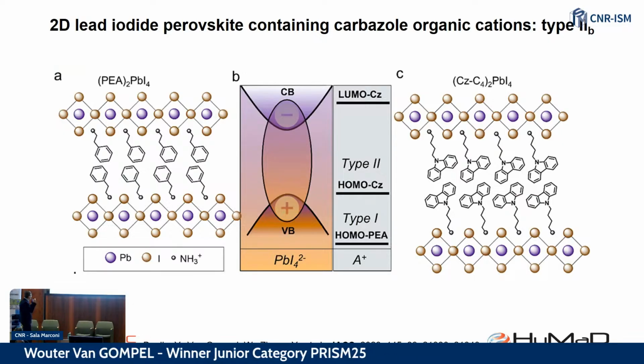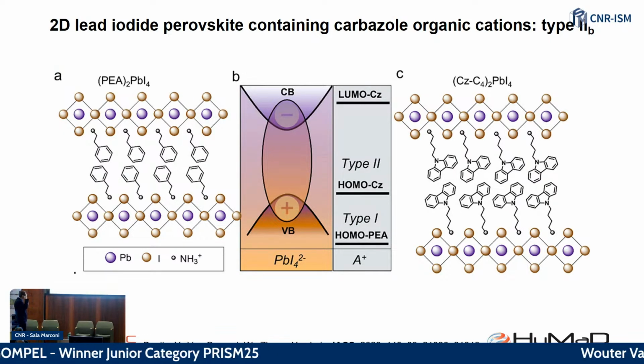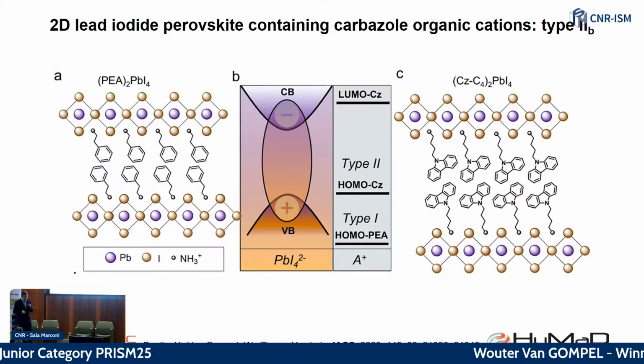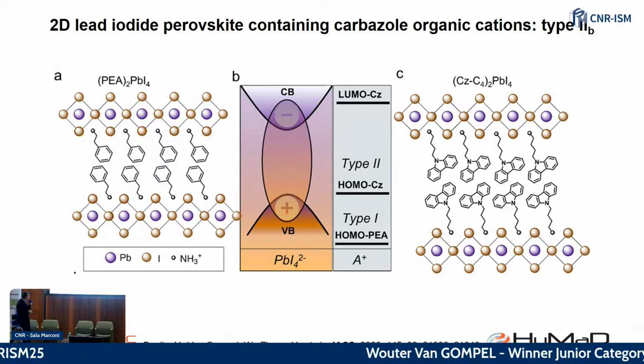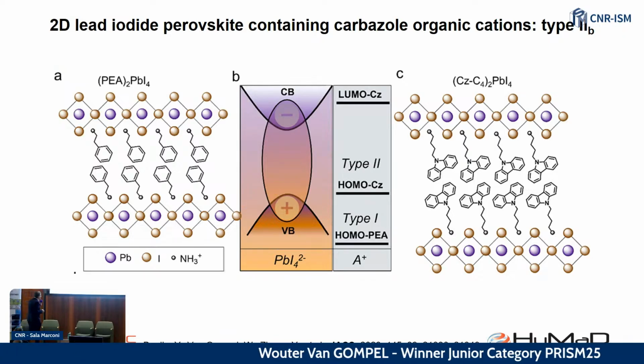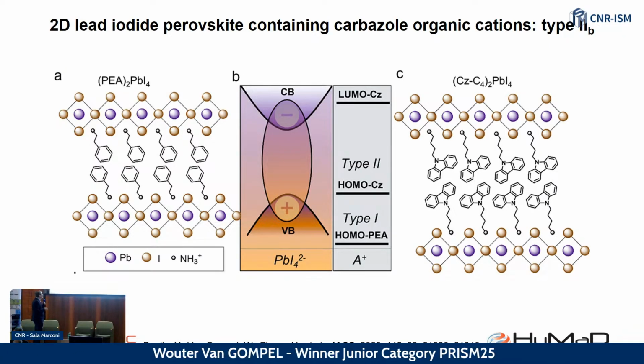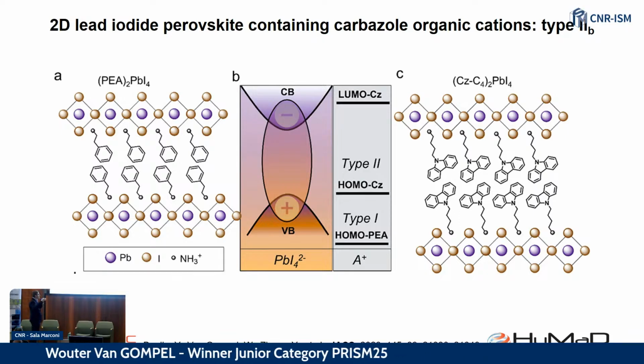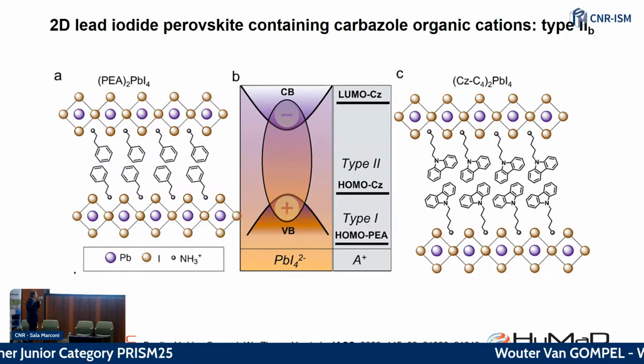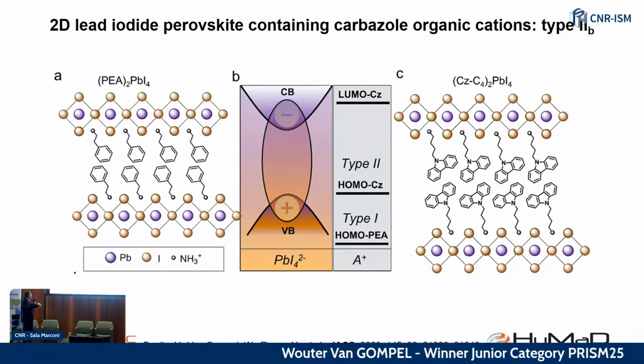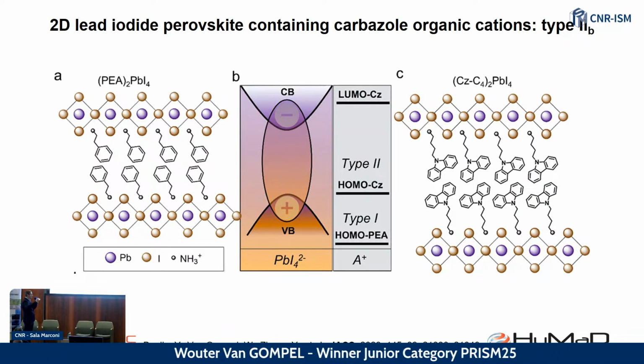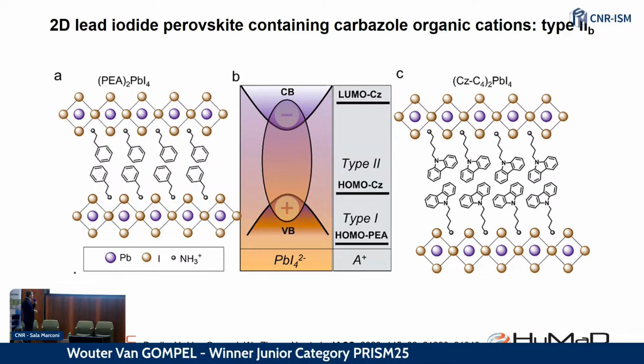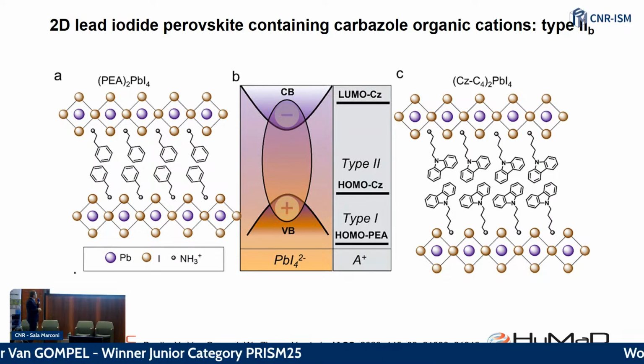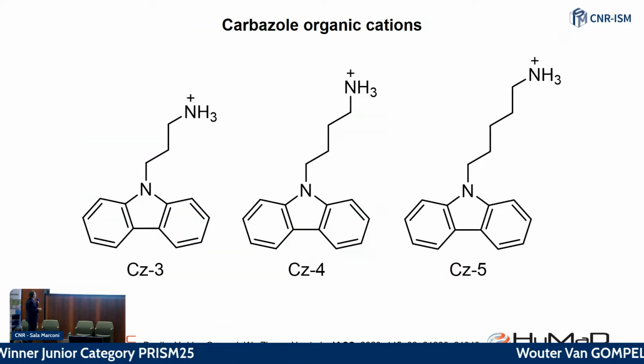An example that we published in 2023 in JACS, together with colleagues from the University of Cambridge in the UK, was based on this carbazole organic molecule. The interesting thing there is that the highest occupied molecular orbital of carbazole is above the valence band of the inorganic framework, while the lowest unoccupied molecular orbital is above the conduction band. So you get the type 2 staggered alignment, and it's one of the first examples of that class.